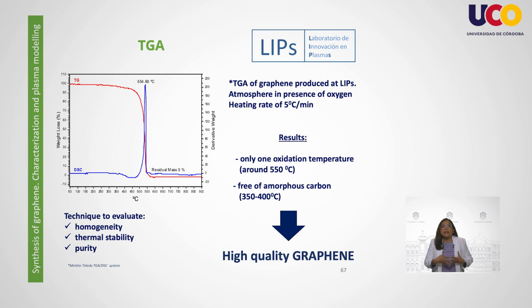And finally, the TGA is a complementary technique for the measurement of thermal stability of materials, homogeneity and purity. This technique can help us to confirm the elemental composition through the burning temperature of a species. Regarding graphene, TGA is a useful tool to determine the functionalized graphene or functionalized graphene oxide weight loss under aggressive temperatures. Here we can see the decrease of mass in certain temperature ranges, which can be associated to the uptake of moisture, oxygenated groups, and nitrogen compounds.